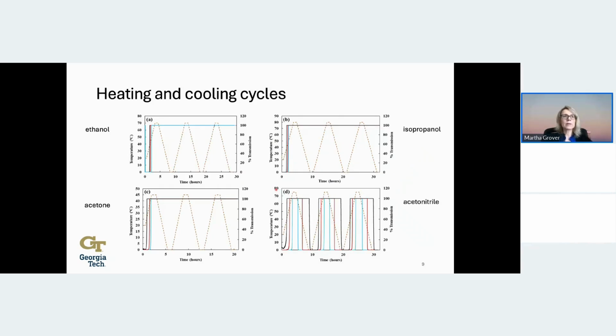So here is what we saw for 3 heating and cooling cycles in each of our 4 solvents. Let's start first with ethanol. We had three different experiments here where we used different concentrations, different amounts of crystal. When we would heat, we would hit a temperature here around 40 degrees where the crystal would disappear. On the right axis is the percent transmission. When we get to 100% transmission, we take that as the point where the crystal has fully dissolved, and we use the corresponding temperature as our solubility.